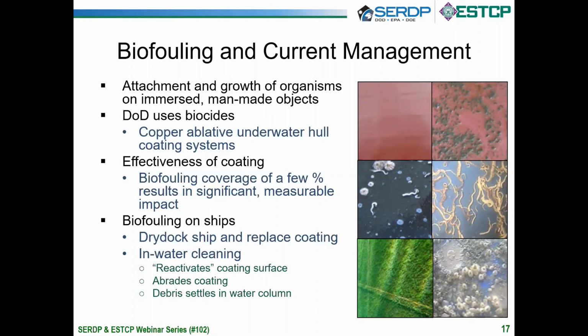through the use of in-water cleaning. The in-water cleaning of ablative anti-fouling coatings serves multiple purposes. One, it removes the biofouling, which is the immediate problem. But fortunately, it also tends to reactivate the coating by removing what we call a leached layer through this abrasion between a rotating brush, for example, and the coating surface. So this restores the rate of release of the biocide and extends the effective service life of the coating. There are some environmental concerns about this process that I'll identify later.